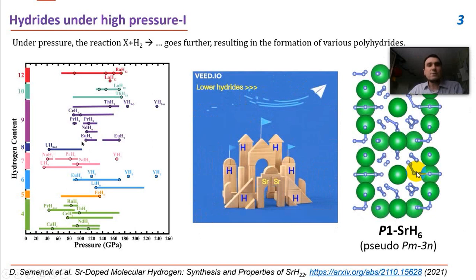Okay, if we continue to increase pressure, we will get nonahydrides such as neodymium H9, praseodymium H9, cerium H9. And after that, the most important class of superhydrides, the high temperature superconductors. These are decahydrides, such as lanthanum H10, a cubic compound, thorium H10, and proposed yttrium H10, and so on. Of course, we can continue to increase the pressure and the hydrogen content in the unit cell of compounds, and the richest compound synthesized at this moment is strontium H22, synthesized by our group.